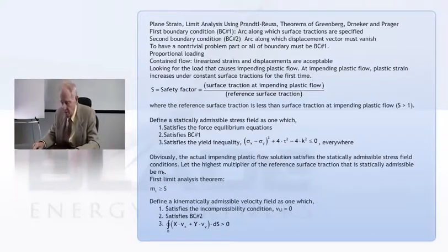And so that's what they call M sub s, the highest multiplier for the reference stresses. And the first so-called limit analysis theorem is that M sub s has to exceed S, hmm, or rather the relationship is a complicated way of saying that the load you calculate this way is less than the actual load that it takes to collapse.